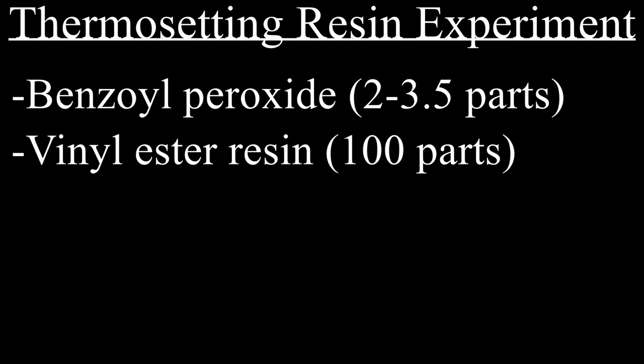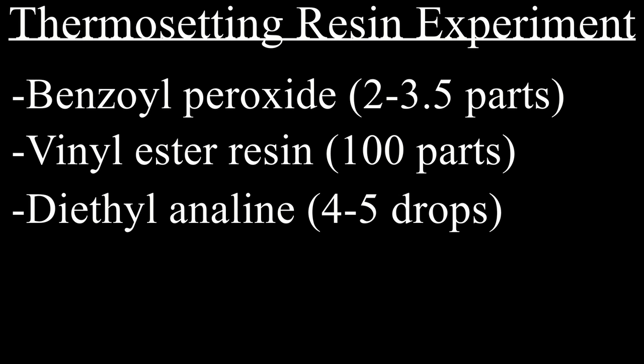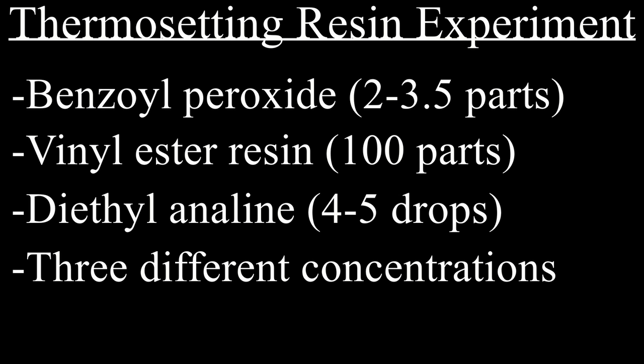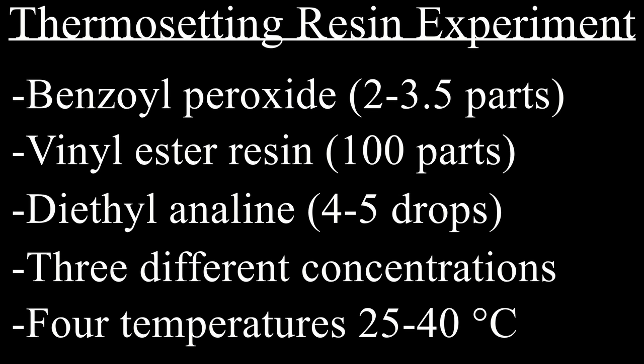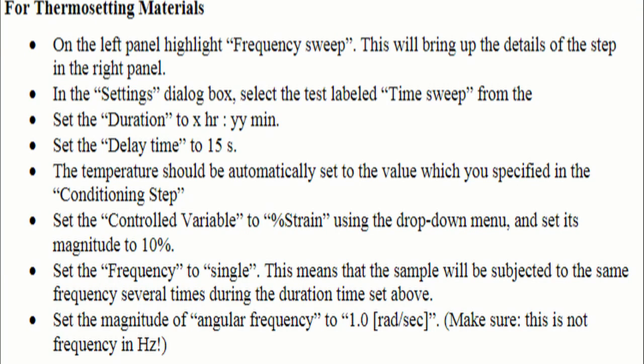We will now discuss a thermosetting resin. The thermosetting material is made up of benzoyl peroxide, vinyl ester resin, and diethylaniline. Keep track of the exact quantity you use to more easily vary the proportion of BPO. In this experiment, 3 different concentrations will be used between 4 different temperatures, 25 to 40 degrees Celsius. Calibrate and prepare the rheometer similarly to a thermoplastic experiment and copy from the written manual the inputs for experimental procedure. The goal is to plot storage modulus, loss modulus, and complex viscosity against time as the thermosetting material cures.